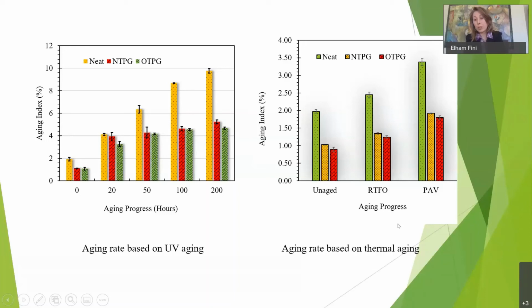We also did the thermal aging. So what if the sun is not that bad, but it's very hot and oxidizing? So we tested, this is another test in the lab without UV radiation, just thermal oxidation. And we saw the same thing here. The neat, I mixed up the colors here, so don't worry about comparing the two figures. Here, neat is green. So you can see the neat, and then the plastic ones, when it's unaged, and when it's short-term aged is the middle, and this one is extensively aged, like an old road.